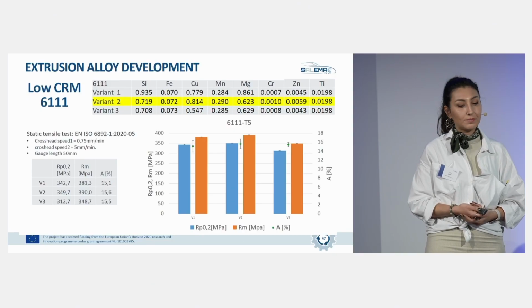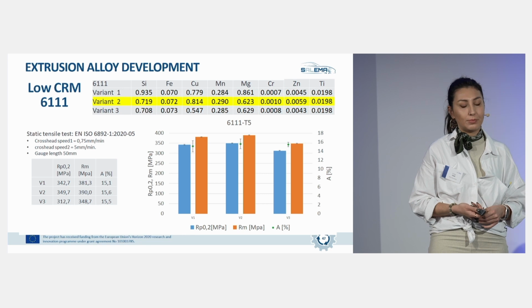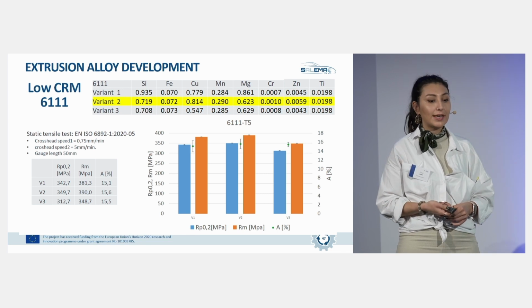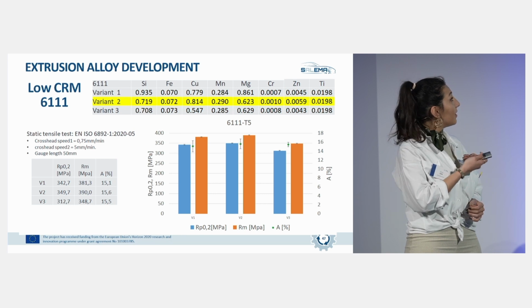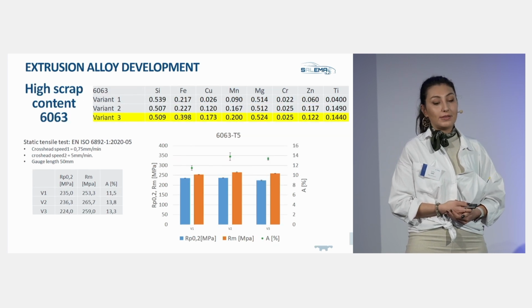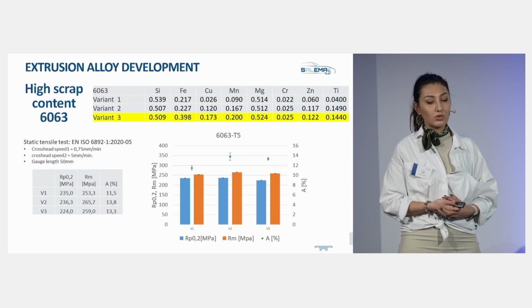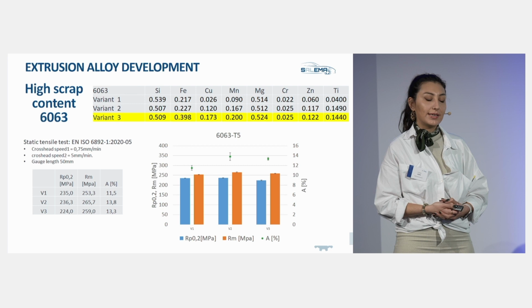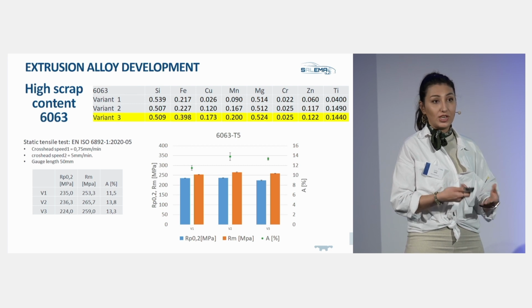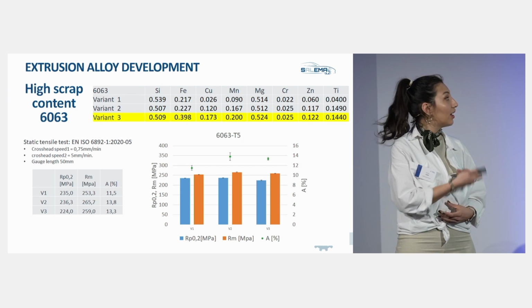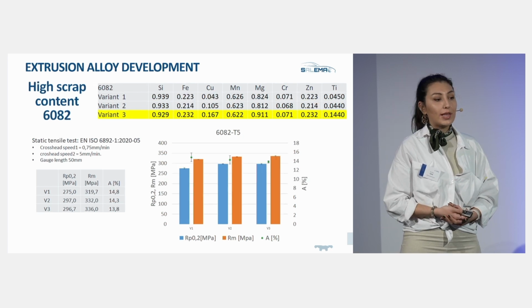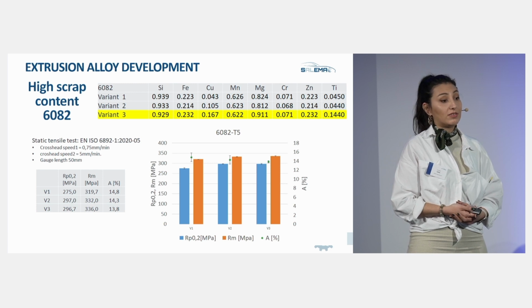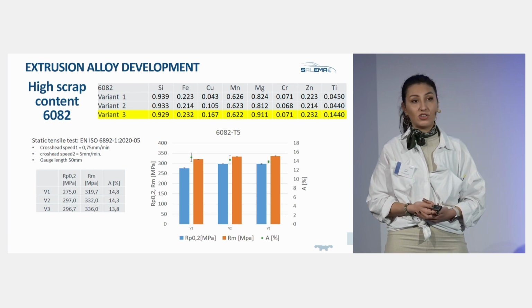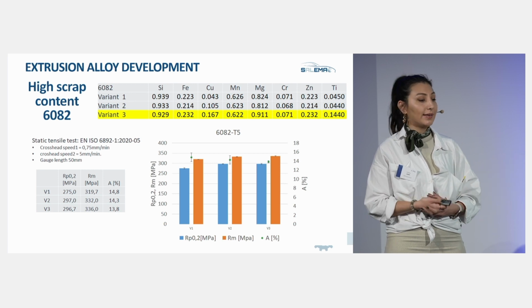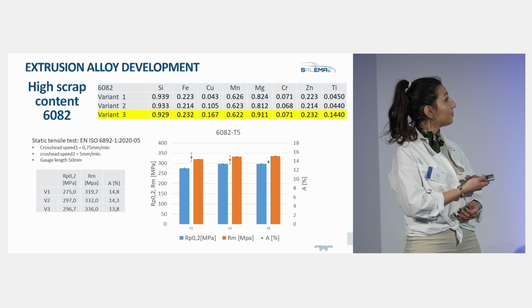Upon this, low CRM content alloy 6111 has been chosen with respect to its mechanical properties, especially from bending results, and variant 2 has been chosen. After that, 6063 alloy has been tested mechanically, and with the results of the mechanical properties and the bending test, variant 3 has been suggested to be upscaled by ASAŞ. And finally, 6082 alloy has been developed, and 3 different variants have been tested, and variant 3 has been suggested to be upscaled, again, with respect to its mechanical properties.